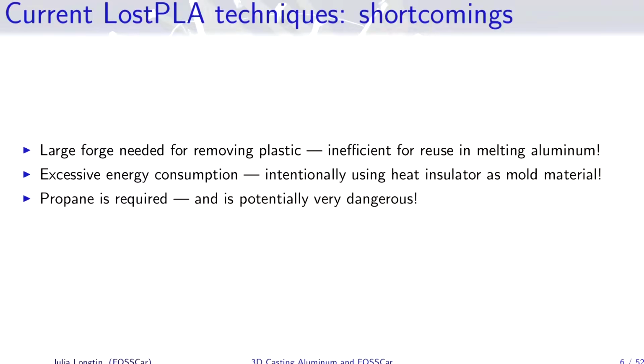So what I've been looking at is, of course, with a 24-hour delay, it's hard to have any sort of turnaround, and the results are not necessarily guaranteed. I've been having roughly a 1 in 3 success rate out of my process here, and that has to do more with the pieces that are in common with lost PLA than anything I've been managing. You have to sit there and burn propane for most of the day, which is a whole lot of energy. And in practicing this technique, we've actually run into several accidental fires. So not burning oneself down is important.